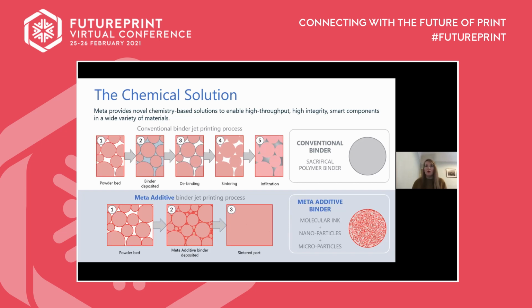And that binder contains an organometallic or a molecular component to the ink. That's solution-based. When that sees the powder bed, it forms a lovely conformal coating of either metal or ceramic, depending on the material that you use. And that lightly holds the powder together. It actually reacts the powders together. So you get a proper chemical metallic or ceramic bond forming, and that holds it together.